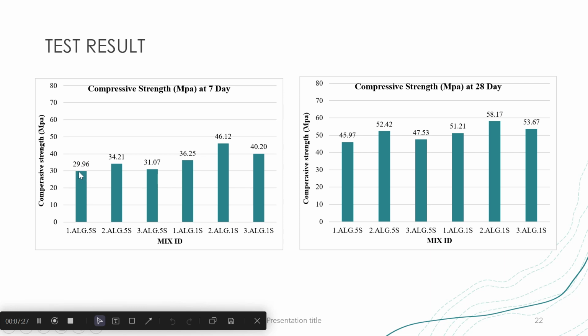value of 29.96 megapascal, and the high value for 46.12 after 7 days of the casting. And after 28 days, the compressive strength for the first mix shows the value of 45.97 megapascal, and the high value is 58.17 megapascal.